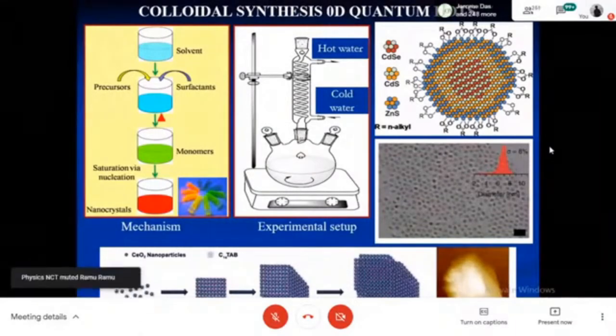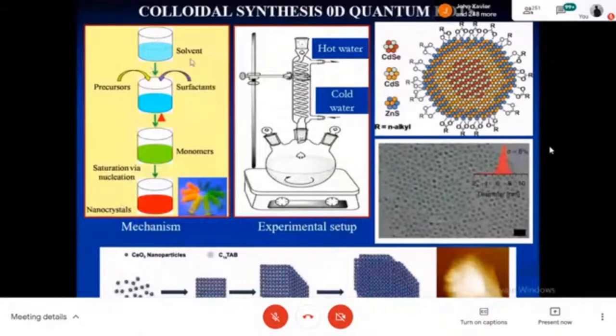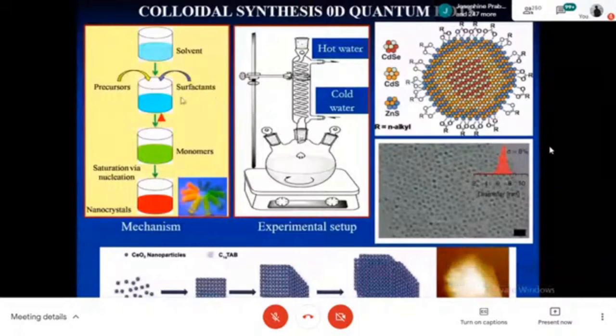structures. And this is the very easiest way of making quantum dots. What we do is take the material and a proper solvent and dissolve it, and you form the precursor, and the precursor has to be mixed with the surfactants. And the role of the surfactant is that we are talking about very, very tiny particles, which is less than the Bohr exciton radius. Because these are all done in a self-assembly process, once it reaches the critical stage, the surfactants will encapsulate the size, so that there will not be any further growth of these particles beyond its limit of Bohr exciton radius.